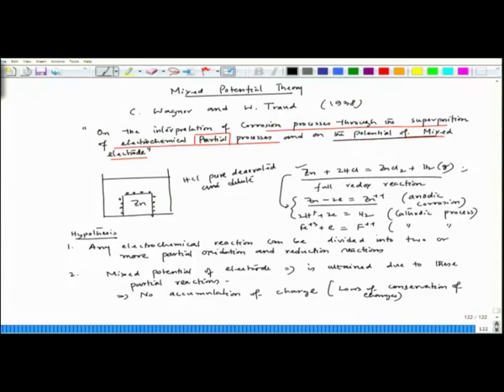So, now we see that there is one cathodic reaction, or there are two. For example, if I consider this particular reaction, there are one cathodic and one anodic reaction. If there is no net accumulation of charge, that means all the charges are balanced. In that case, for this reaction there could be a current density IA, the anodic current density for the anodic process, and for this reaction there should be IC, the cathodic current density. So, IC should be equal to IA at mixed potential. This is the second hypothesis.